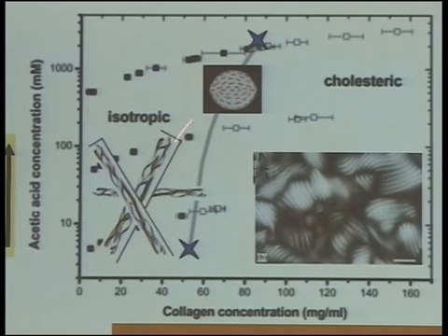Not determined experimentally, there is a band where you have biphasic equilibrium. So here you have biphasic equilibrium, and inside the biphasic equilibrium, like in other liquid crystal systems, you tend to have tactoids. So I put the tactoid there to show that in this chimney, if you will, this kind of chimney structure, that's where you have tactoids. They are stable, they're not going anywhere, they're micron size, they're stable. They are anisotropic,